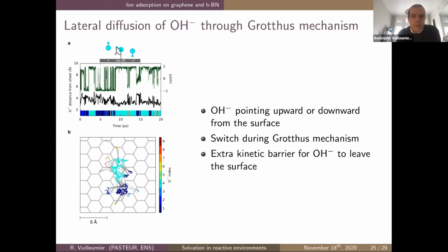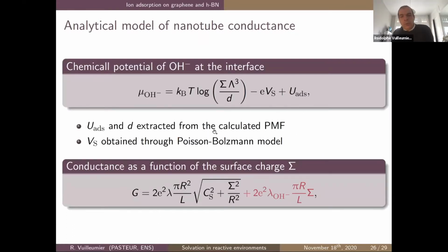We not only have creation of charges on the surface, but we have also transport of OH minus on the surface, so a surface current. And when we try to reassess the experiments which were not measuring directly the surface charge, but which were measuring the conductance of the nanotube as a function of pH, for example, there first principle MD is at its limit, because we model here only one OH minus. If there is adsorption of a few OH minus to large surface charges around Coulomb per square meter, then there are electrostatic interactions between the OH minus. You have formation of a double layer. We don't have any counterion in the simulation, and so we need to put all this. This will be much too large to put in a full first principle MD simulation that contains all the ingredients, enough counterions to describe the double layer, etc.